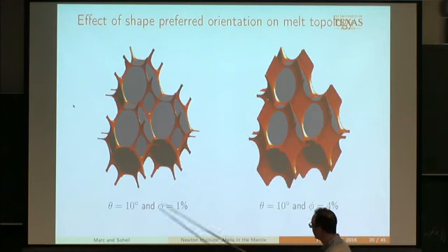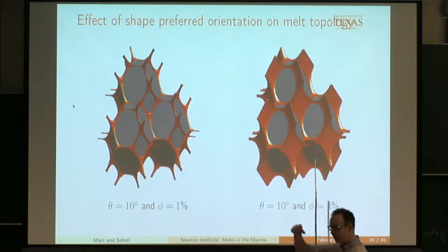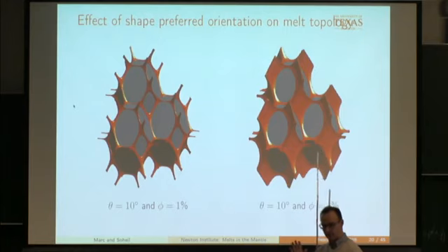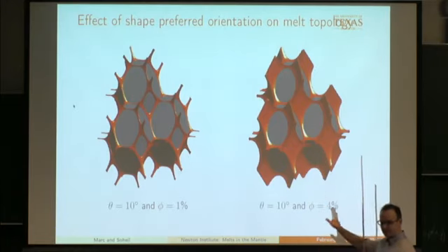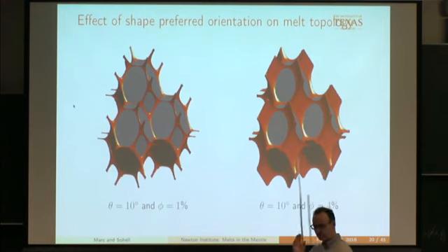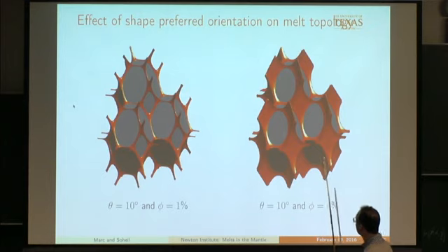And this is for dihedral angles that are low. Essentially, if the dihedral angle is below 60, there's a tendency for the melt to distribute itself onto the faces that are parallel to the direction of stretching. And when exactly this happens depends on the dihedral angle. And I think in an irregular medium, of course, there won't just be one transition, but one after the other, the faces will get wetted that are roughly parallel.